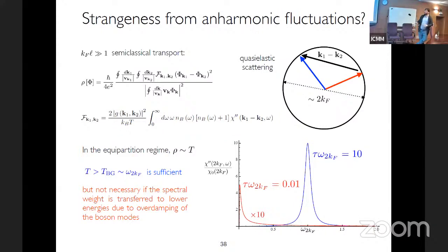But actually, if quasi-particles are not well defined, these peaks always move to the left because there is this transfer of spectral weight. So these temperature scales are always a few Kelvin, several Kelvin, because the sound velocities are still large. There is only a 30% reduction of the sound velocity of the Phason with respect to the phonon, and the sound velocities of the phonons of graphene are large because carbon is very light and graphene is very stiff. So these are very large numbers, and that's the mystery, how you can extrapolate this behavior to very low temperatures. The reason maybe is that this is not the characteristic temperature scale of the problem, because all the spectral weight of these bosons is moved to much lower energy. So maybe this classical behavior could be extrapolated to lower temperatures. That's kind of the speculation.